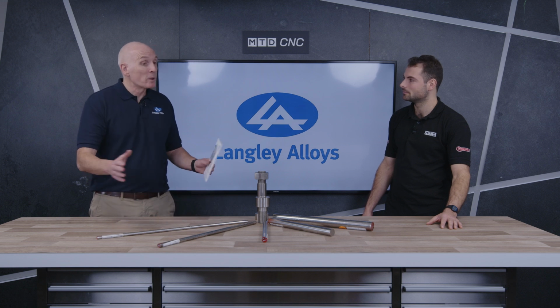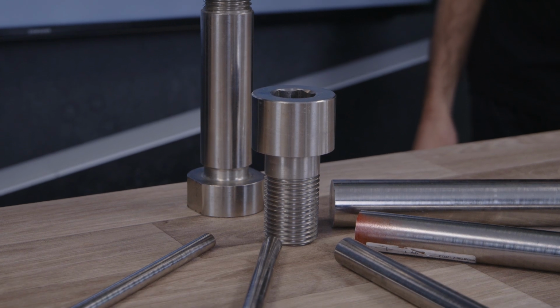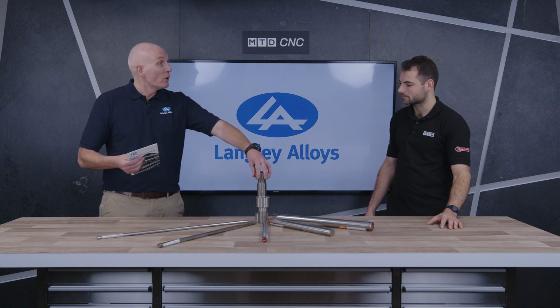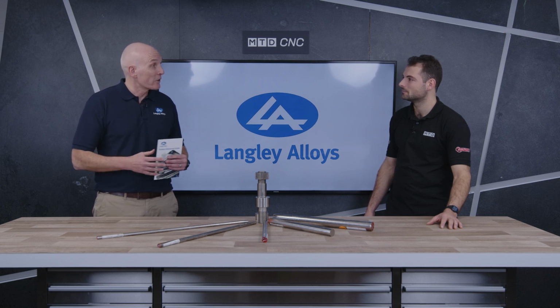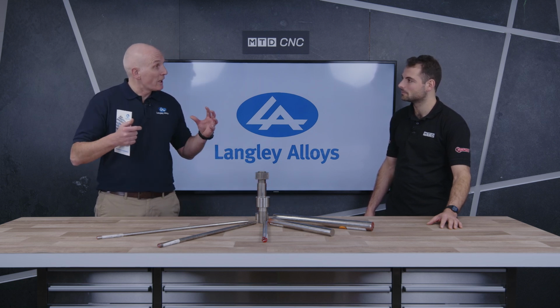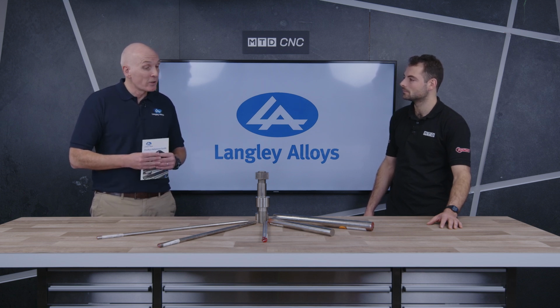You can machine it down from a raw billet. There are other ways to manufacture it as well to save material. I'd be doing a disservice to the fastener guys to talk about all the different shapes and sizes and designs, but you can imagine small diameter bars will be machined on a sliding head into small components, or thread rolled to put a long thread along a length of bar. The larger diameter bars will be machined to form the nuts. If you've got a fastener with a large head on it, maybe it will be forged, so you're not wasting lots of material. You're keeping the original diameter for the shaft of the bolt, but you're upset forging to form that head more cost effectively, and by forging it you retain the good physical and mechanical properties of the alloy. So there are lots of slightly different ways of making them.